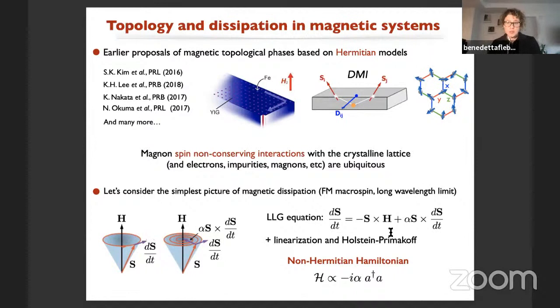Now, if you take this equation, really the simplest equation to describe some ferromagnetic macrospin type of dynamics, and you linearize this equation with respect to the equilibrium position of the spin and invoke an Holstein-Primakoff transformation, you will find that this term here, the one proportional to the Gilbert damping, gives rise to a non-Hermitian contribution to the Hamiltonian. So this was something supposedly known already since a long time, but it wasn't really discussed because we didn't know how to really treat this term.